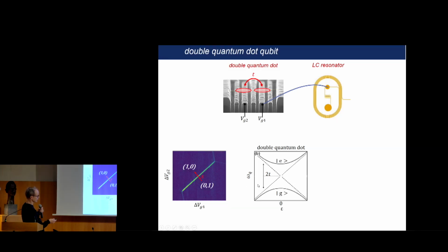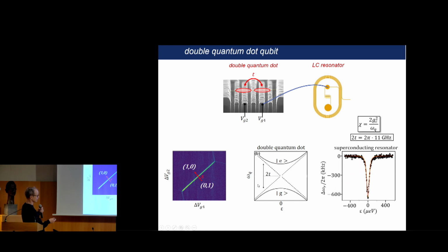And here, I show you the detuning, which is the energy difference between the left dot and the right dot. And so when it's 0, here it's when we have the resonance between the left and right dot, and then the qubit frequency is given by the couplings, the tunnel strength, sorry. So the tunnel strength here. And we can measure the qubit here by measuring the frequency of the resonator. And you see here a reduction of the frequency of the superconducting resonator. And from this reduction, we can get the tunnel coupling that is equal to 11 gigahertz. So from this simple expression.